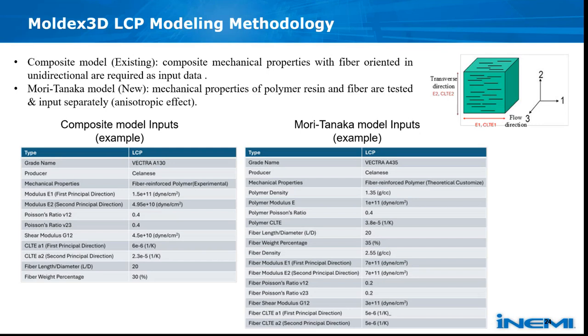And this is the most used method since everyone can characterize the material if they have the ability to make the sample following some measuring standards. The left chart is a sample of the input by the composite model. You can see the fiber and the polymer base are treated as a whole and show strong anisotropy in different directions. And the second generally used method is we can characterize the mechanical properties of the fiber and the polymer base separately, and we input the data and combine them with the composite model, like with a theoretical model such as the Mori-Tanaka model. The right chart is a sample of the input by the Mori-Tanaka model. Here we can see both the polymer base and the fiber are assumed isotropic. However, due to the fiber shape, we get anisotropy when they are combined into the composite.